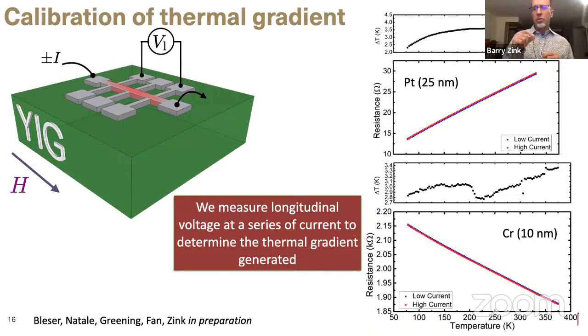In our case, when everything is small, there's just this sort of micron scale wire that is put on top of the platinum. We can measure its actual resistance. The parameters are a little simpler. There are fewer interfaces to deal with. Maybe it's just because I'm more familiar with these types of issues, but I have more confidence that I know what the thermal gradient is in this experiment.